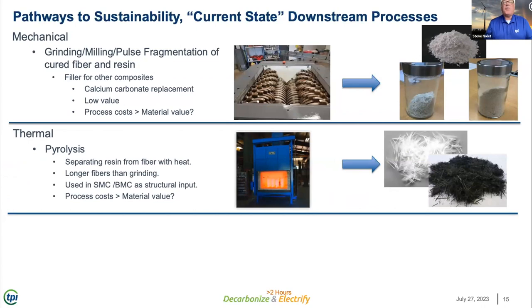Similarly, if we have thermal processes, such as a pyrolysis operation, through zero oxygen combustion of these materials, we can separate fiber from resin with heat. We can obtain larger fibers as a result. Discontinuous fibers in general, we don't feed continuous full blades, so they're reduced in size to feed the pyrolysis process. But these materials can find their way into sheet molding compounds, bulk molding compounds, or some other material systems that we'll talk about in a little bit.